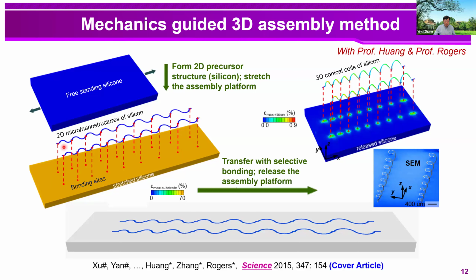In the meanwhile, we can use a microfabrication technique to create a patterned 2D thin film. In this example, the film is made of single crystal silicon and shows a serpentine configuration. Then we integrate the patterned 2D thin film with the pre-stretched elastomer substrate. Here, by using techniques of surface chemistry, we can create strong covalent bonding selectively only at the red sites. The other places in blue are simply weak in adhesion and can pop up easily from the substrate surface after release of the pre-strain.